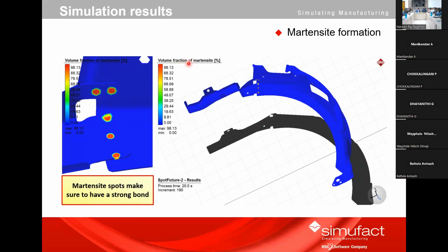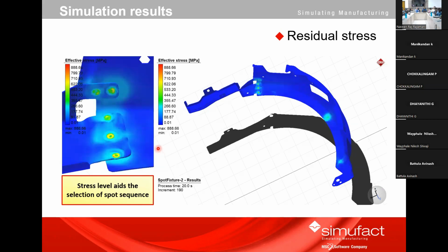Then we can also see the different fractions of phase transformations happening, like the fraction of martensite. You can see the martensite spots, making sure that there will be a stronger bond at those locations. These are some metallurgical aspects that we can monitor to get a correct idea of the process. And coming to the mechanical aspect, like stress levels, it is the selection of the spot sequence: whether the chosen spot sequence will give us the correct distortion or residual stress outputs that we want or not.